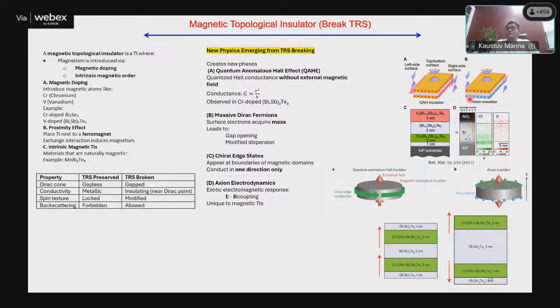Now, if both of the edge states are gapped, you will think that this is an insulator, but this is not an insulator, because other conditions are automatically satisfied. Like for example, strong SOC is still valid. Band inversion is still valid. What is the consequence of them? The consequence is that you have the edge state gapped out, but the band inversion still intact in the system. It gives rise to a Chern insulator kind of.